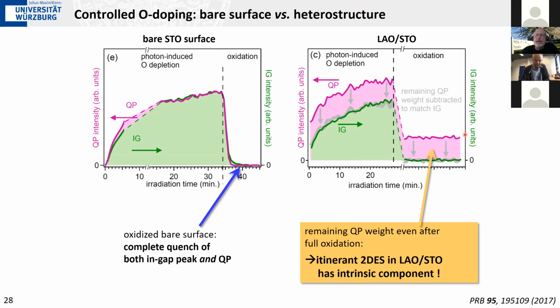And the critical thickness of the LAO-STO is then related to the fact that the energy of formation for these anti-site defects is a function of this inner potential, or the polar discontinuity, I should rather say. So they can derive a very nice, relatively consistent picture out of this. So polar discontinuity plays a role here, but it's not the simple electronic reconstruction picture as was often sketched out.